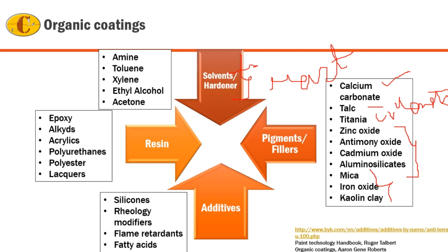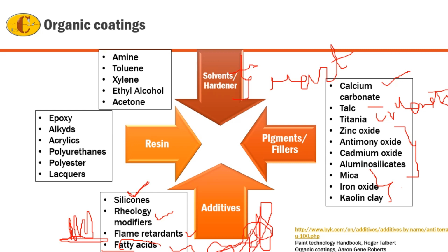And mica, iron oxide, kaolin clay may be used to increase the coating resistance or to prevent easy water penetration. In addition to these, you may have some additives to change their properties. So the silicones help to get a better resistance to moisture absorption and also better adhesion to the substrate. Rheology modifiers are used depending on whether the coating has to be sprayed or painted. Flame retardants are used in offshore platforms to prevent the fire on the platforms. Fatty acids are used to increase the molecular chain length so that the density and the compactness of the coating increases.